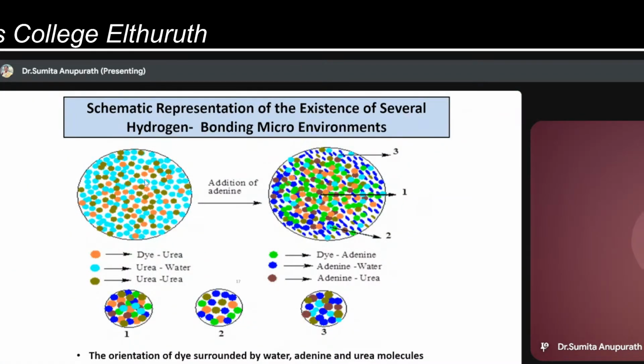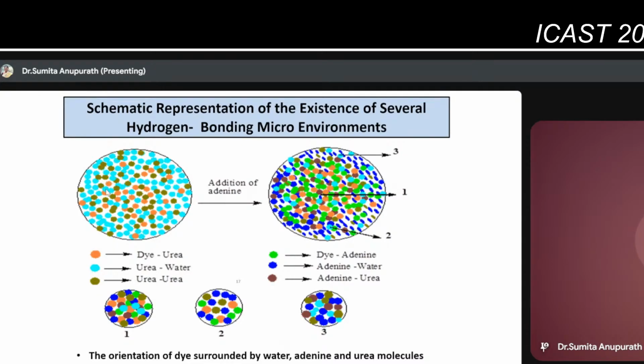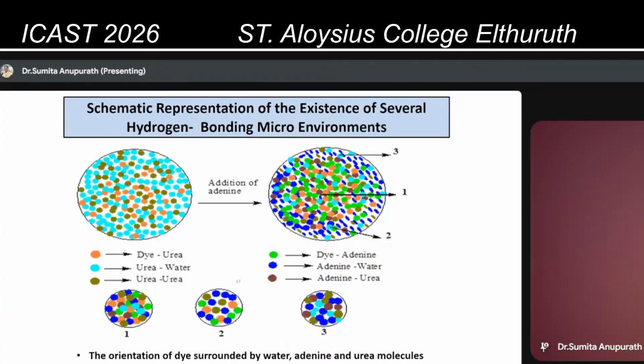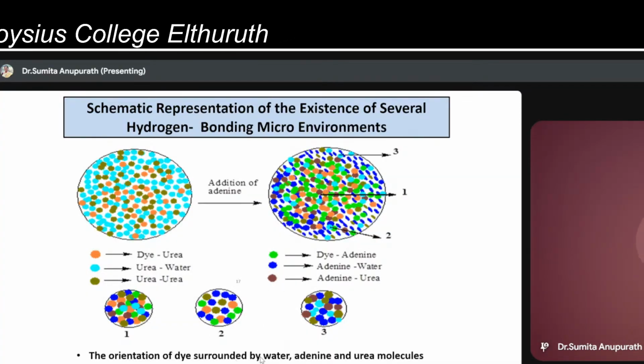This is a dye-urea system, in which the blue color shows the urea-water system. Along with that, we have dye-urea and urea-urea interactions also. To this system, we added adenine, and successfully adenine was able to push away the dye from the close proximity of the urea, and that led to the formation of various co-spheres, or we can say the dye was surrounded by water in one of the co-spheres. It was also surrounded by adenine molecules, and in another co-sphere we could find some urea molecules. So several such co-spheres were formed in the aqueous phase.